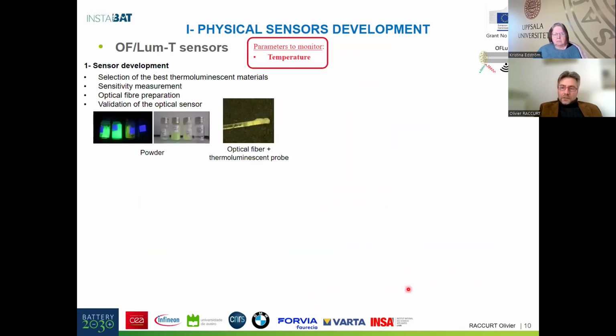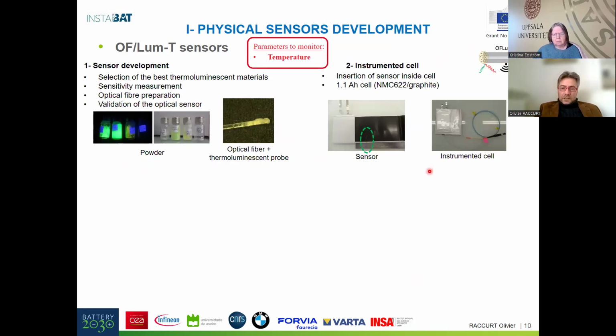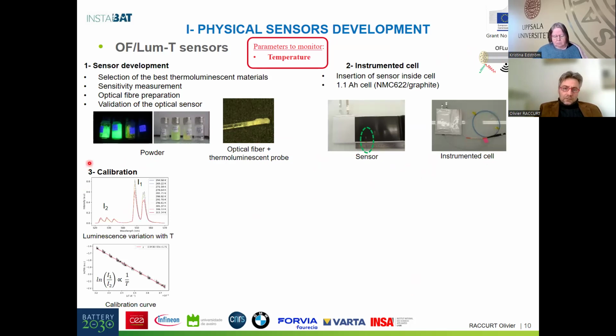Another kind of sensor developed with optical fiber is a luminescence sensor based on optical material to monitor the temperature. During the project, we worked on selecting luminescence materials with good properties, and put this material at the end of the fiber to develop the sensor itself. And we also tested the sensor in the cell. You can see here the integration of the optical fiber into the pouch cell. And we validated the calibration of the sensor.